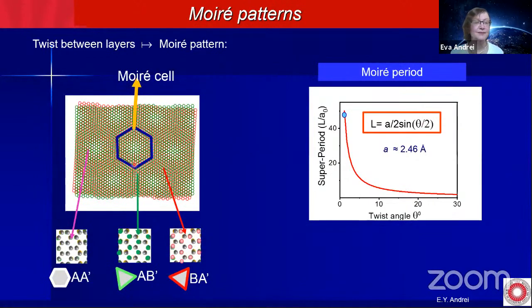So what we have here, what are these bright and dark spots? The bright spot corresponds to the atoms in the top layer being precisely aligned with the atoms in the bottom, so that they completely eclipse the bottom ones. Whereas the darker region corresponds to an A atom in the top layer sitting on top of a B atom in the bottom layer, and the B atom in the top layer having no neighbor underneath. So this gives you these darker regions, which are actually triangular. Here, these are the atoms that have neighbors underneath, and we have two kinds of such neighborhoods. One where the B atom on the top layer is on top of an A atom in the bottom layer. So this is what this pattern is doing here.